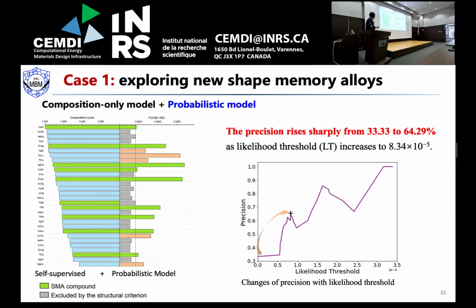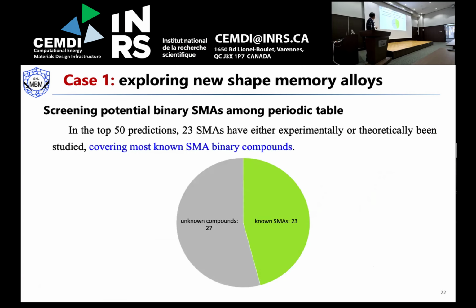Okay, so by combining these two ways, the self-supervised learning method and also the probability model, we predict the top 50 alloys, and we found among them 23 are already known alloys, but we still have the 27, which is unknown compounds, and never discovered.